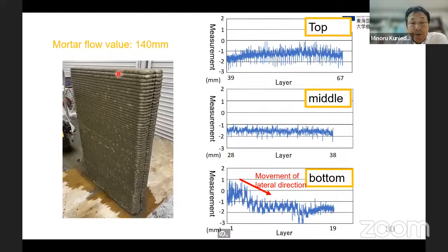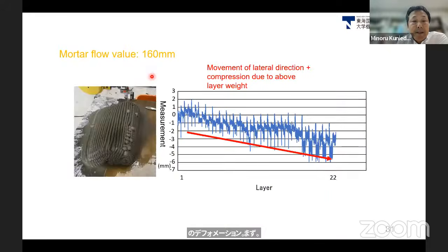And this is a result of the wall with the mortar flow value of 140, a stiffer mortar case. In the initial part, we observed the same behavior, even in the stiff mortar case. But as you can see, with the stiff mortar, no deformation was observed up to the top of the wall. And then in the mortar flow value of 160 millimeter case, lateral movement was observed in the bottom layers, in addition to the deformation due to compression by the weight of the above layers. So finally, we had collapsed members at the 22nd layer.